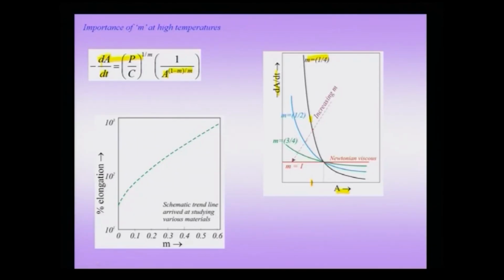That means, for a given value of A, say for some value of A1, if I have a material with higher strain hardening or strain rate sensitivity, then the reduction in area would be smaller. So, you will actually be on the lower curve rather than the higher curve, and if it is even higher, like 3 by 4, then you will be on an even lower curve.